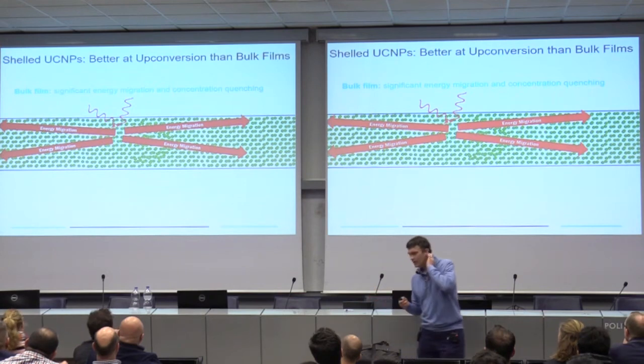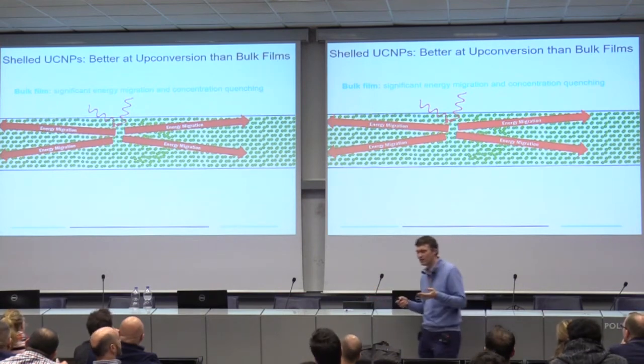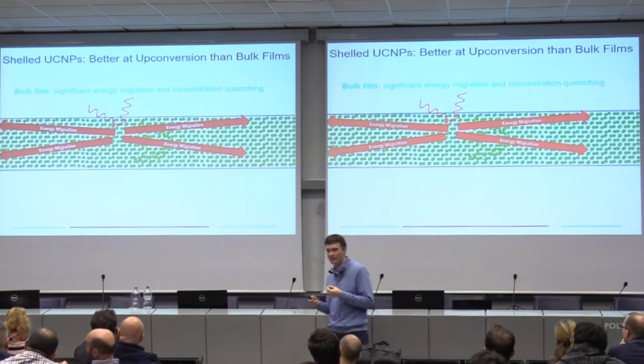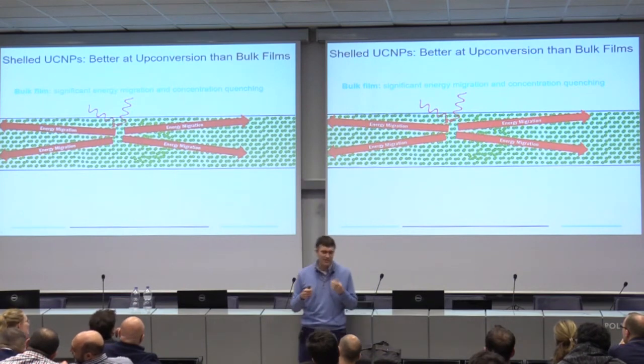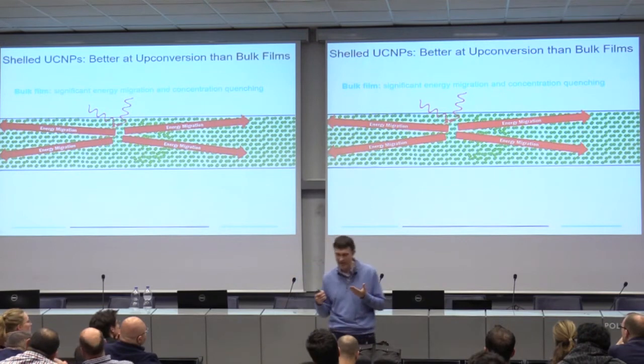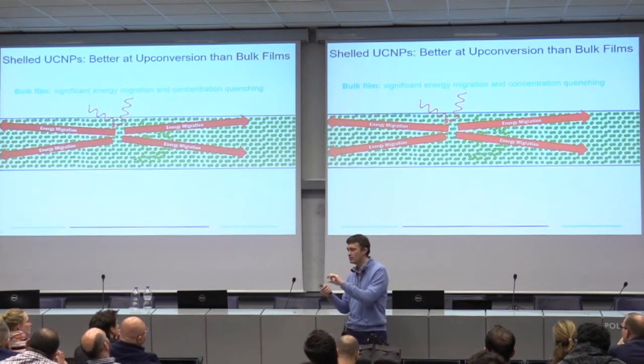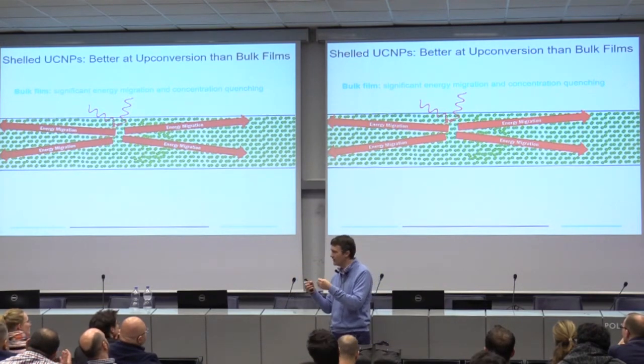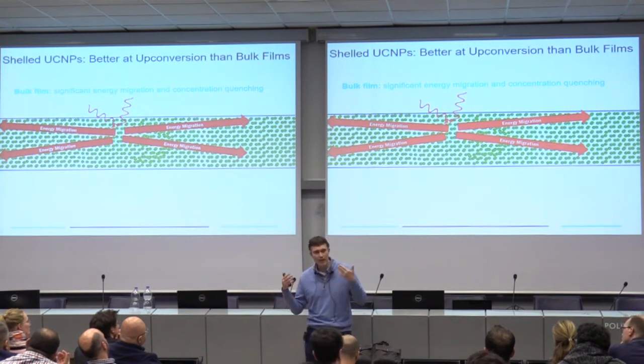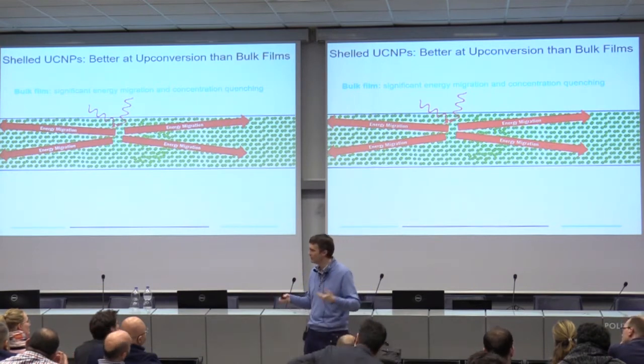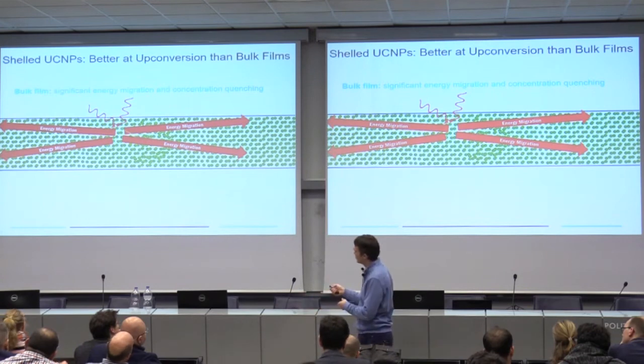And in fact, it turns out it's not even that they just could get bright. It turns out that something somewhat not intuitive became clear, which is that if you actually take your nanoparticles and you design them correctly, and you make a film of nanoparticles, they can be better at upconverting than a bulk crystal. And the reason for that has to do with this so-called energy migration.